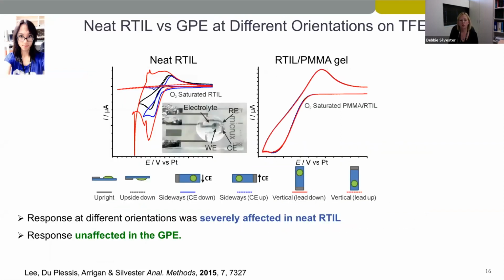And so just to show the proof of principle that the gel polymer electrolyte is very robust, we looked at the oxygen reduction response when we changed the orientation of the electrode. So with a neat ionic liquid, when we just have a droplet on the surface, you can see the black line shows the ideal 1 electron reduction when the electrode is upright. But then as we change the electrode to different orientations, we change the response quite significantly, and then eventually we lose all of our sensor signal when the electrolyte has flowed off.